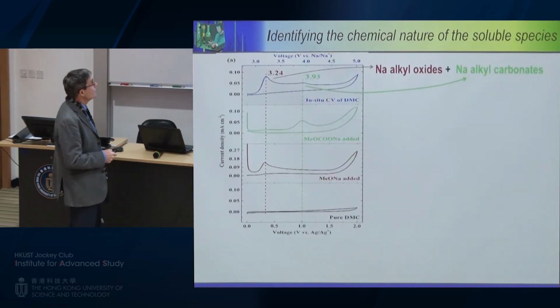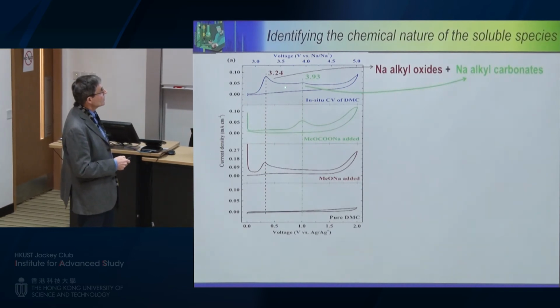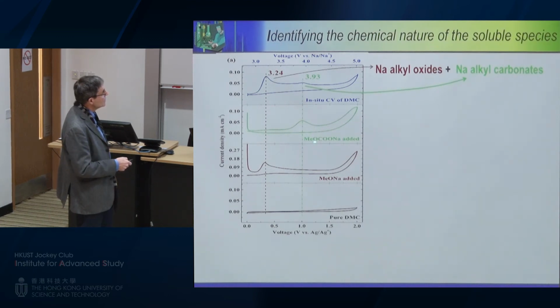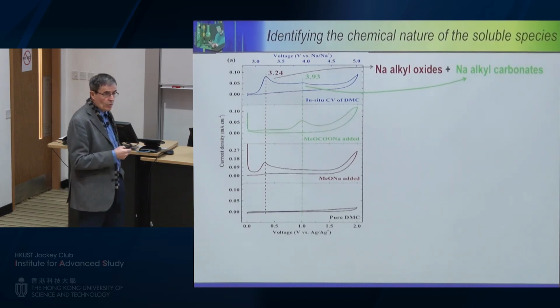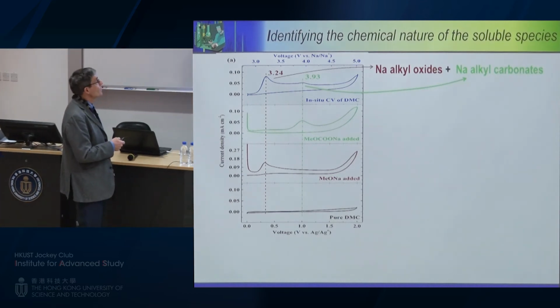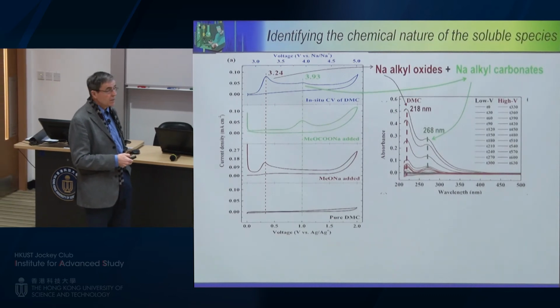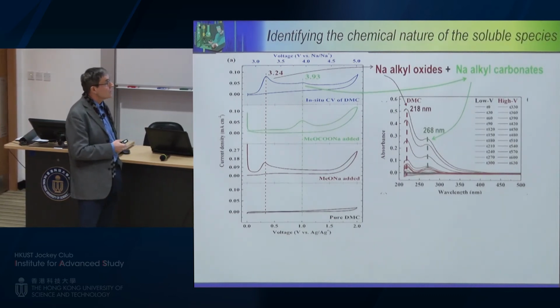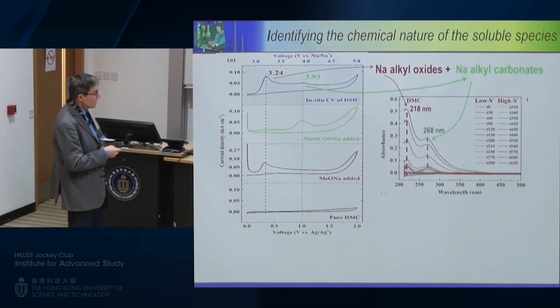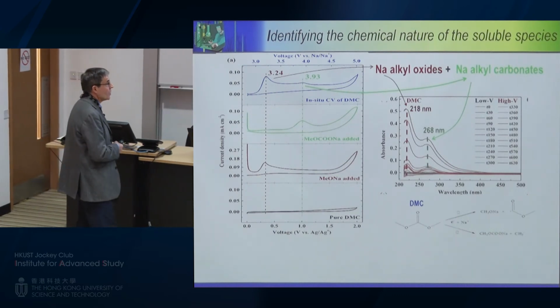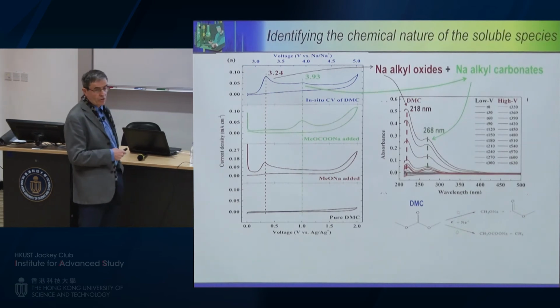And when we do so, this is more or less what we observe. The top here, remember, is the cyclovoltammogram that we collect between WE2 and C1 in DMC that I showed you before. And now, this is our reference compound. Look here, I have the sodium alkyl oxide. Look at the peak here. Bingo. Perfectly at the same position. That's what we observe in our experiment. Now, if I look at the alkyl carbonate, here again, methyl alkyl carbonate, it corresponds to the peak at 3.93. So this indicates that we obtain this type of species. We could also explain the absorbance peaks that we have in our UV visible spectra, which means that in this case, we have a decomposition of DMC into these two surface species according to the reaction mechanism.